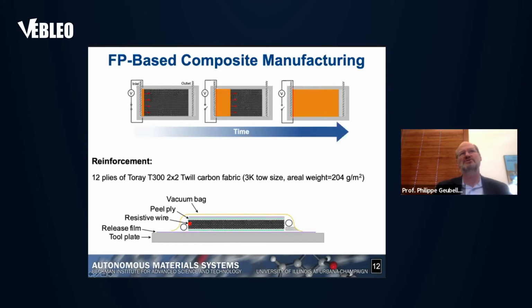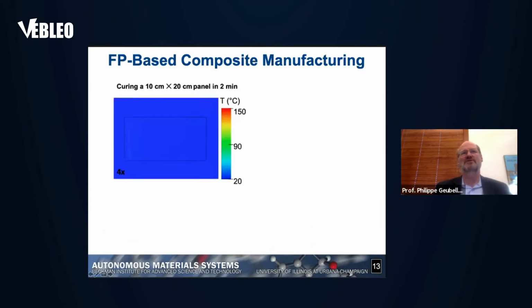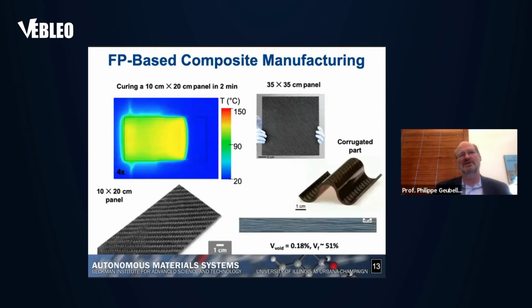But then after that, we introduce some thermal trigger by passing a current to a wire here. And then after an initial transient phase, we see that the front starts to propagate across the entire composite part. And here's an actual video. This is an infrared picture taken from the top. This is a 10 centimeter by 20 centimeter panel. We start the process by running a current through the wire. And then we just turn it off and the front starts to propagate completely on its own across the entire part. And we managed to make a panel like this, what would be out of an autoclave, in about 2 minutes.